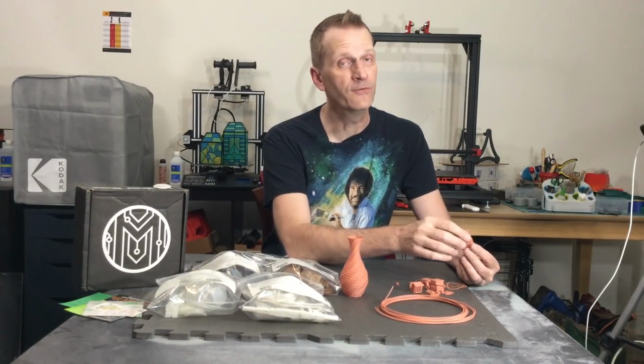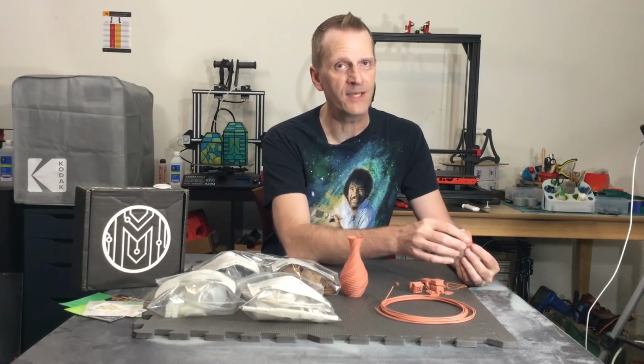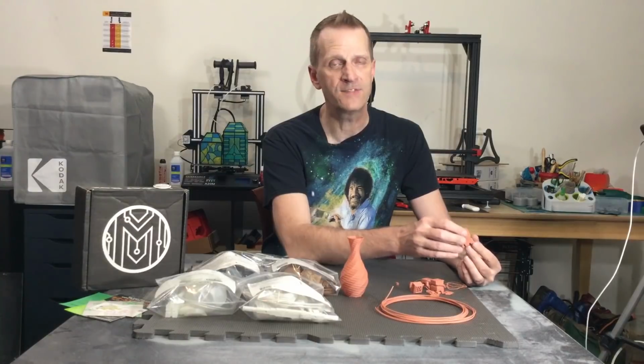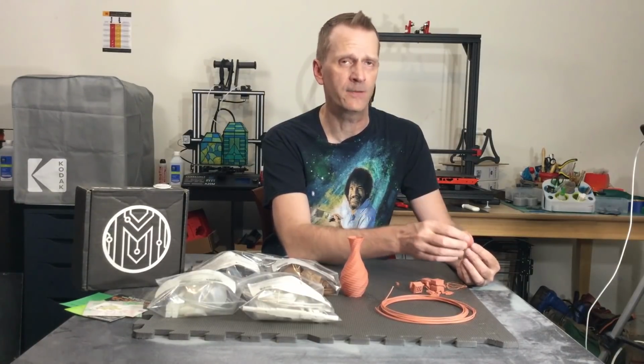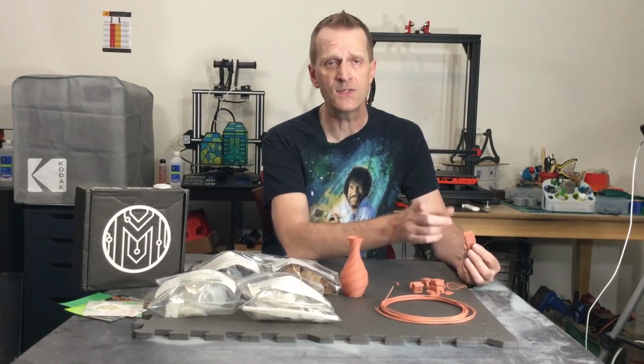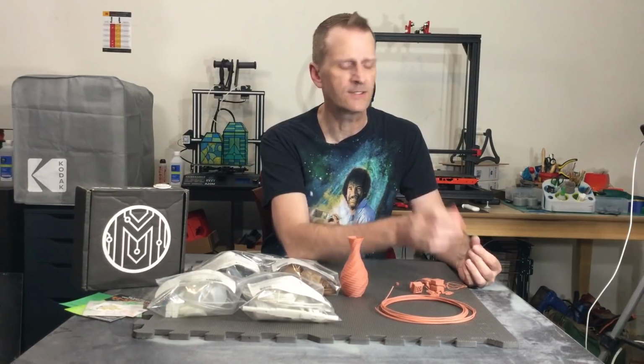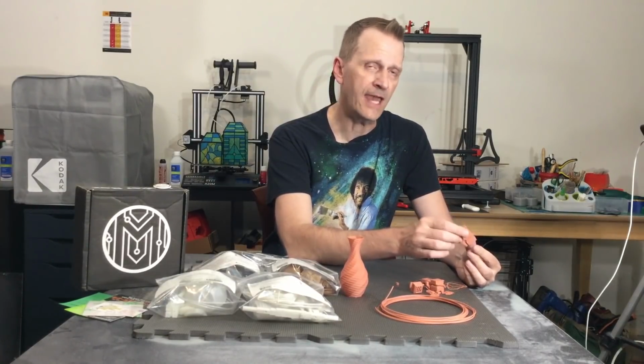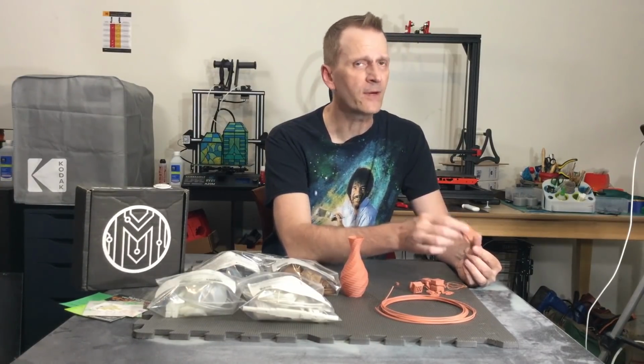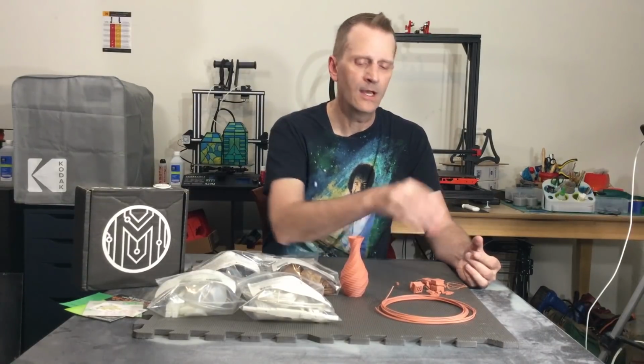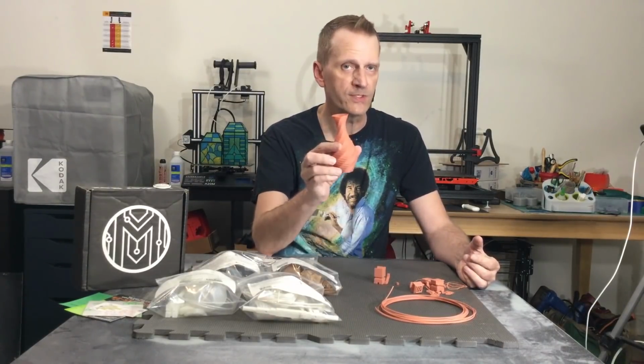So 240 C on the hot end for a PLA-based material, and 105 C on the bed, which is super hot in my opinion for printing it. But this is a unique material, and I'm willing to make exceptions. So once the Cali Cat was done, which printed out quite perfectly for such a high temperature, I moved on to the rose twist vase.